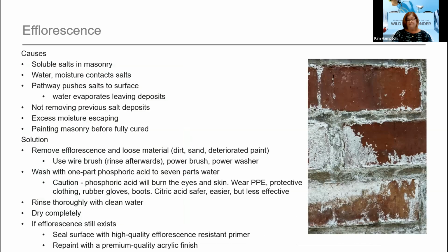Efflorescence. In mild cases, efflorescence can be removed by dry brushing with a soft nylon or bristle brush. However, if the salt deposits continue to redevelop, corrective measures may be necessary in order to resist the reoccurrence of efflorescence. White fuzzy deposits, soluble salts, form on concrete, brick, block, stucco, mortar, or other masonry surfaces when exposed to moisture.